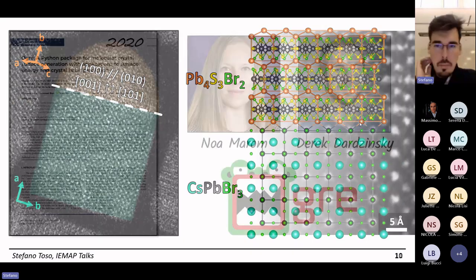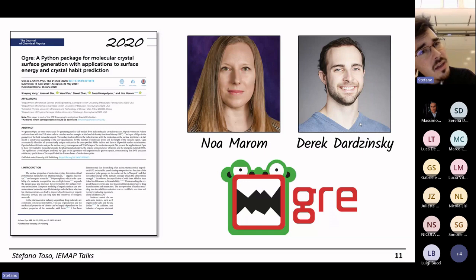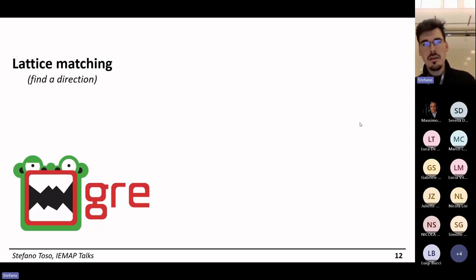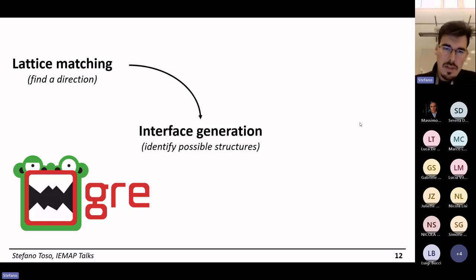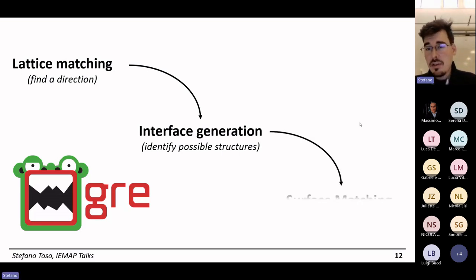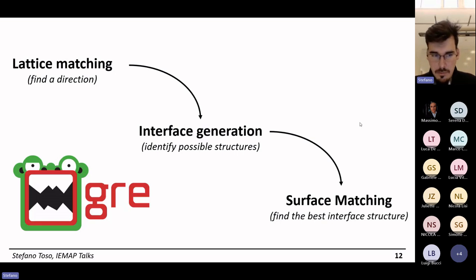What we did was we teamed up with a group of theoreticians from the Carnegie Mellon University in the United States who are active in the design and programming of codes for epitaxy predictions. Their library is called OGRE. And we teamed up to design a new framework based on OGRE that simplifies this job and is more oriented towards colloidal nanomaterials. And this is how it works. So the first thing that you have to do is to check the directions, the lattice directions in which the two materials like each other. After you have identified one or two promising options, you can prepare possible models of this interface. And what's next is that you actually optimize these models of the interface to find the best possible configuration, attribute a structure to the interface, and attribute an energy ranking, right? So you can also have an idea whether the interface will be stable or not.